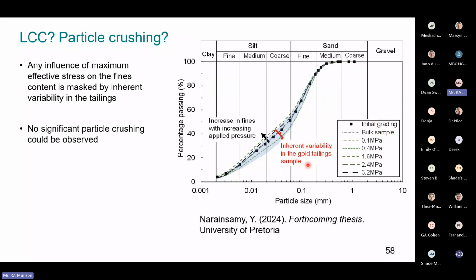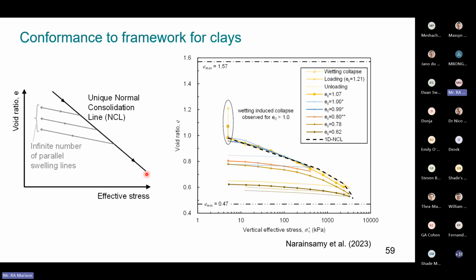And luckily, Yashay has done a whole bunch of tests where 32 different grading samples were taken throughout the course of his PhD, and the grading curves plotted within this envelope over here. So there is some inherent variability in the gold tailings. And only one of the samples that we took over here plotted outside of the envelope created by the other 32, meaning that any particle crushing, however marginal, that we could have seen was masked by the inherent variability of the gradings of the tailings. So we cannot provide any significant evidence of particle crushing, and under stresses of 3.2 MPa, given what we saw earlier for quartz sands, it is unlikely that we had converged onto a limiting compression curve. So if we put all of this together, the compression behavior of this tailing seems to comply best with the framework for clays.